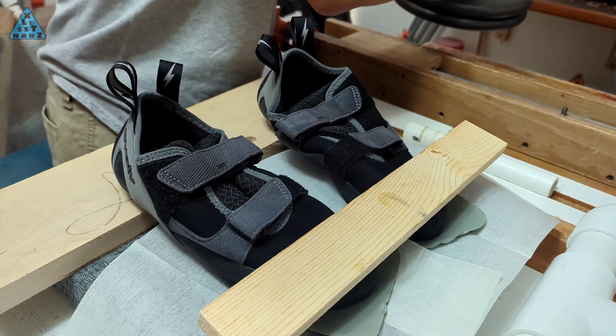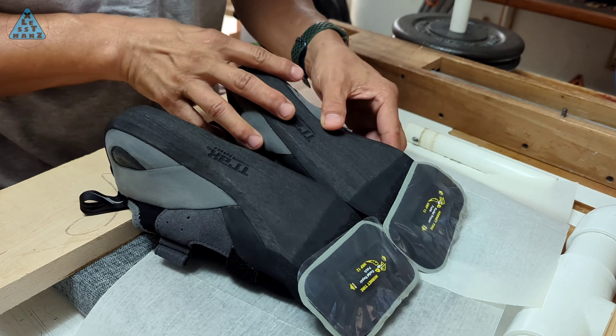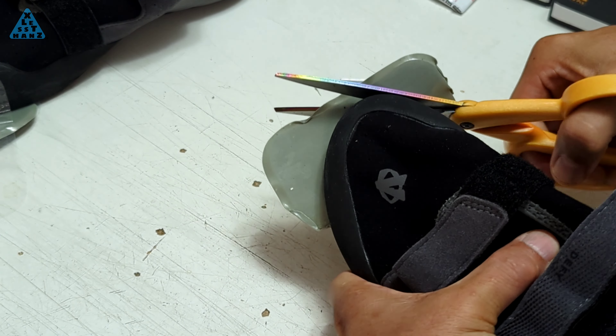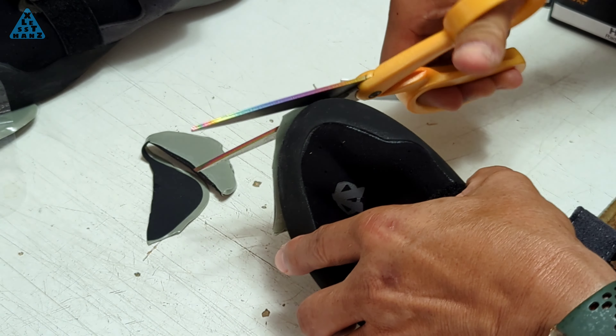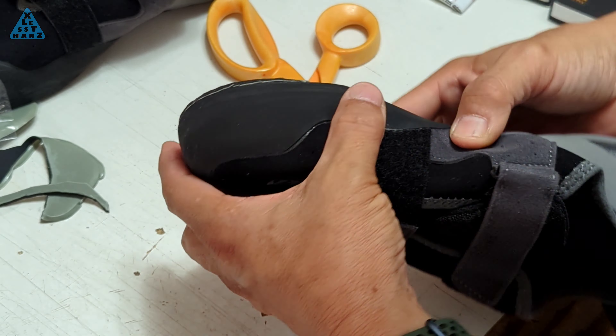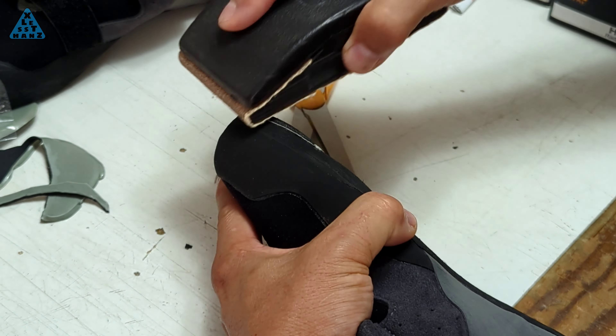It's been 12 hours and now that I know the patch won't easily peel off when handled, I can trim the edges flush with the shoe. A scissors works best for trimming the patch. On the first pass, I'll leave about ¼ inch of patch still protruding from the edge of the shoe. On the second pass, I'll cut the patch flush with the shoe edge. There were some rough spots left behind after trimming — I tried a razor blade to clean up the edge but that didn't work well. The best thing to do after trimming is to go over the edge with a 120 grit sanding block.